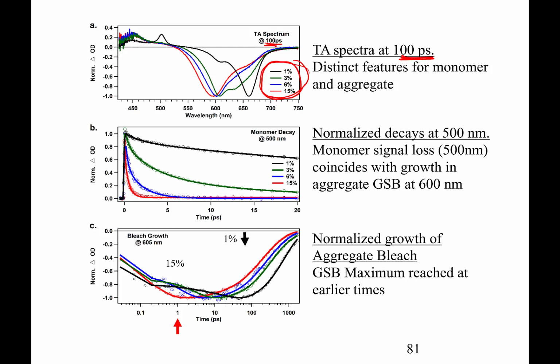again, for very low concentration samples, we have the monomer in here. It's around 650 nanometers at 100 picoseconds. For the high concentration samples, that's 15%, in here we see a peak at about 590 nanometers. We can also look at the normalized spectra, and normalized means they're all normalized to 1 up here at 500 nanometers, and that monomer signal loss coincides with a growth in the aggregate ground state bleach at 600 nanometers. So basically the rate at which this feature drops corresponds exactly with the rate at which the aggregate increases in its intensity, right? So they mirror one another.